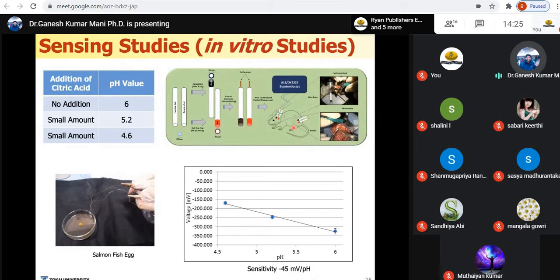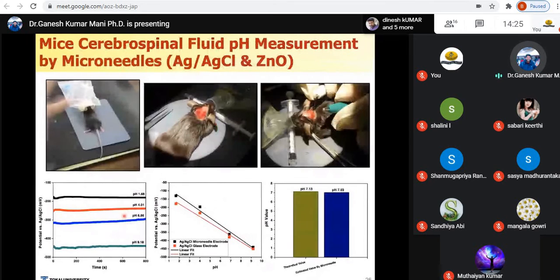So here what we have done is the mice were given anesthesia and then we inserted the microneedle into the mice brain and checked the pH level. The first graph here shows the laboratory experiment. We purchased some pH buffer solution and tested our needle electrode and got the result. That is for reference. And then we ran the same experiment on the mice brain. By comparison, we can get the pH data. Here is the comparison you can see. The yellow one is measured by the commercial pH meter and the blue one is measured by the pH electrode developed by us. And you can see the pH range. The yellow one shows pH 7.13 and the blue one, the microelectrode, shows